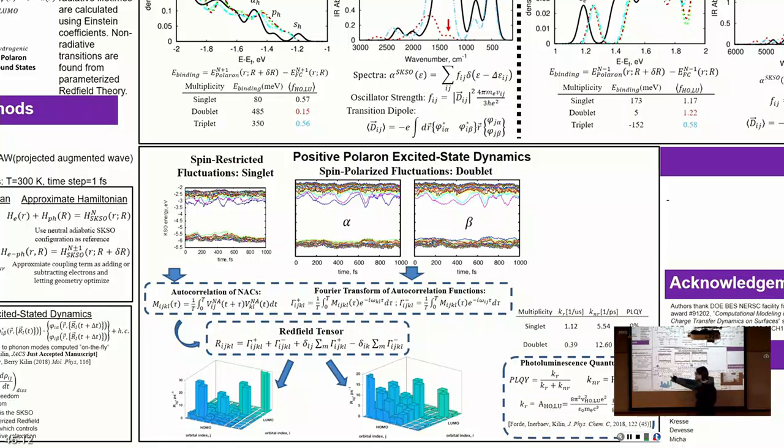The plus or minus describe upward or downward transitions, and the indices correspond to orbital components. But at the end of the day, pretty much all we're left with is those. The upward transitions obey a Boltzmann distribution, weighted by a factor of e^(-ΔE/kT), so they're pretty much negligible.